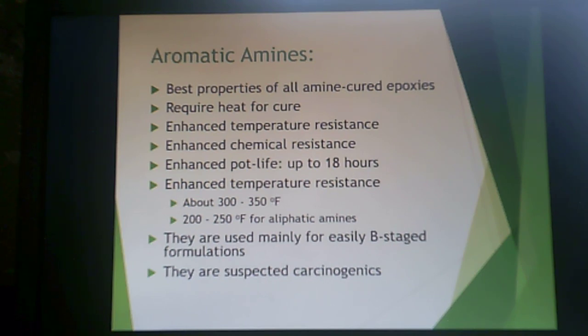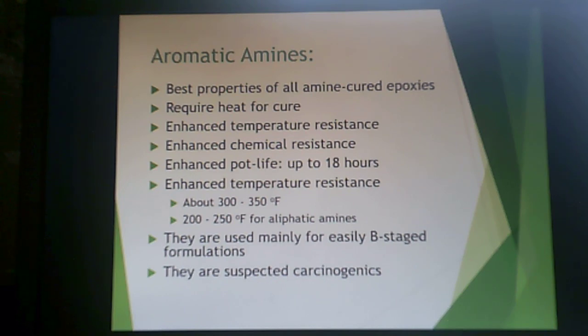Aromatic amines are also used, though overall aliphatic amines are the most common curing agent. Aromatic amines, however, provide the best properties of all amine-cured epoxies. They require heat to cure, which results in enhanced temperature resistance, enhanced chemical resistance, and enhanced pot life up to 18 hours. You get temperature resistance up to 350°F, compared to 250°F for aliphatic amines. These are mainly used for B-staged formulations, but aromatic amines themselves are suspected carcinogens, so sometimes they're avoided for that reason.